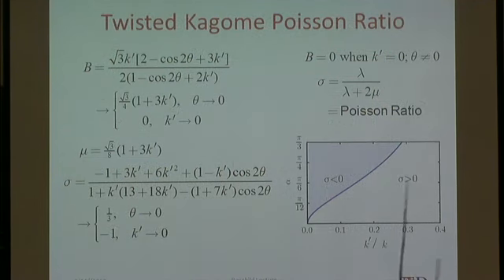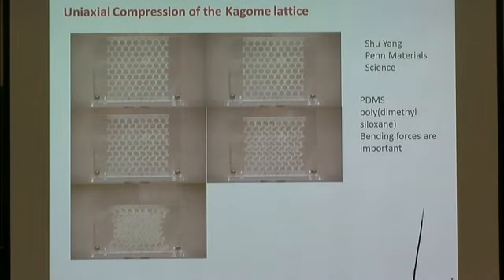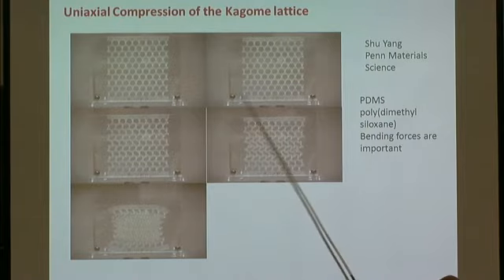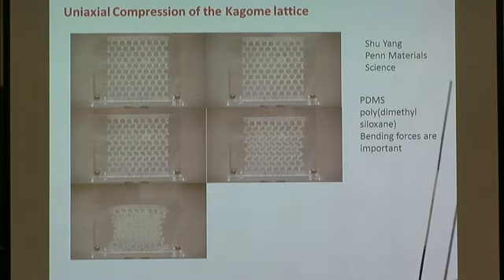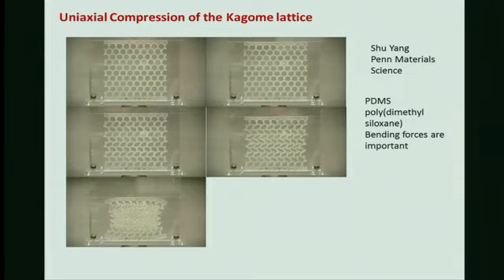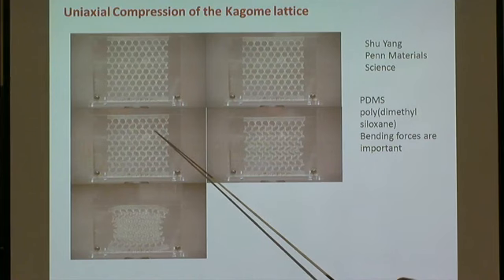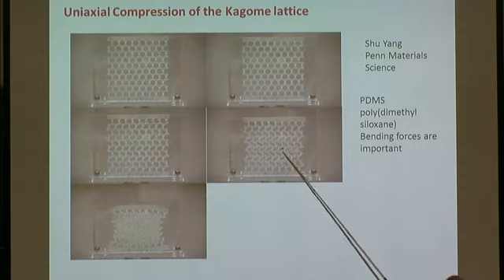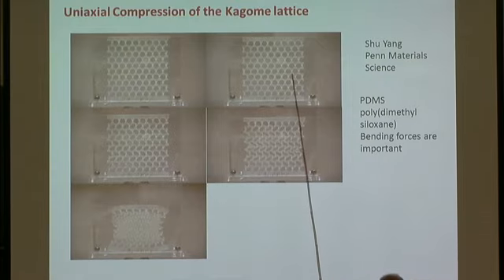So you can calculate, if you turn on K prime, there's a region of negative Poisson ratio and a region of positive Poisson ratio for that simple model. And you know, we actually have started thinking about doing this at Penn. We have Shu Yang, who can do anything with polymers. So this shows a standard Kagome lattice under compression, and it has a bending modulus rather than a next nearest neighbor force. And it can't decide as it's being compressed which way to go, so you get some that compress and stretch out in this direction, and some that do it in the opposite direction. These right here, and you get this sort of herringbone structure. But notice as I do this, there's not much change in this direction.